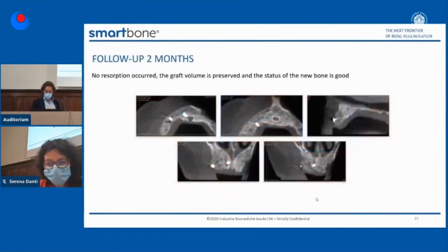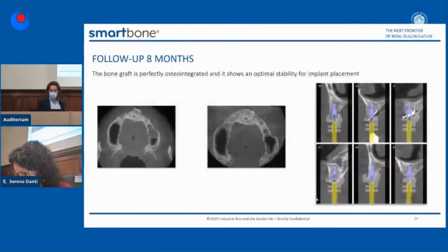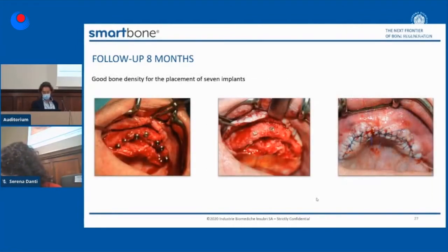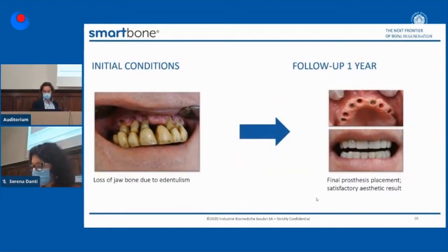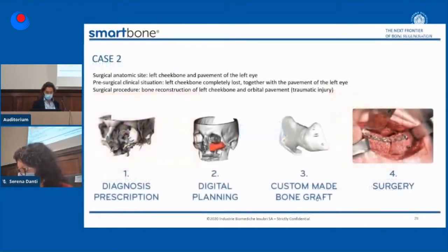Here you can see after 2 months, we have to wait some months for a good regeneration. And here we can see that after 8 months, we have a complete regeneration of the bone. There is no more border, and we also maintain a perfect volumetric shape of the graft. Here you can see the reopening after 8 months. The surgeon decided to place 7 implants, and here you can see the result after just 1 year.